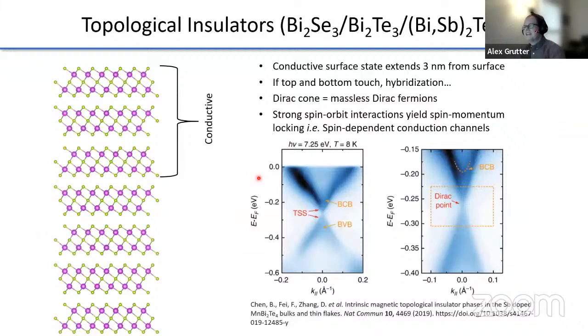So of course, we need to begin with a very brief discussion of topological insulators. Almost all of this discussion is going to be focusing on the canonical topological insulator family of bismuth selenide, bismuth telluride, bismuth antimony telluride. The main points you need to know is that these are insulators in the bulk, but they have conductive surface states that are confined to approximately 3 nanometers near the surface.